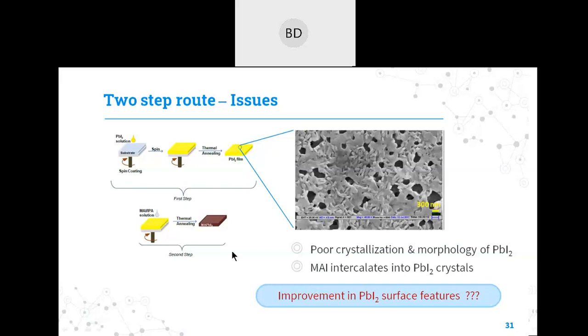If you see the formation mechanism for the two-step route, first the lead iodide film is prepared from the PbI2 solution. If we do some characterization on the lead iodide films, we came to know that the lead iodide film itself has a very poor morphology and crystallization. And the perovskite which is formed from this lead iodide film with MAI goes through an intercalation process. If you take this PbI2 film and put MAI molecules on top of it, then eventually the perovskite is formed by taking the PbI2 structure as the base structure. So as good as the PbI2 structure is, the better the perovskite will be.